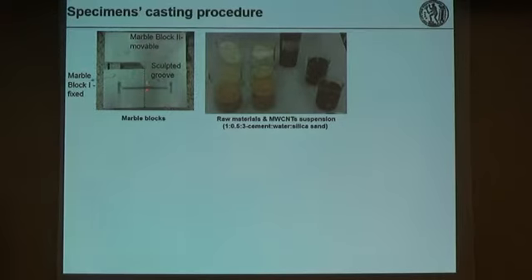In order to do that, we produced several specimens which were composed of two marble blocks. A groove was sculptured inside these blocks. The marble was a Dionysus marble. It's a typical marble that's currently used at the restoration project. For filling the groove, we prepared a cement mortar with white cement and coarse quartz sand, a fine sand and a coarse sand, and the carbon nanotubes were dispersed inside the mixing water with the aid of a new generation polycarboxylate-based ether superplasticizer, which is typically used in cementitious materials, and with the application of ultrasonic energy.